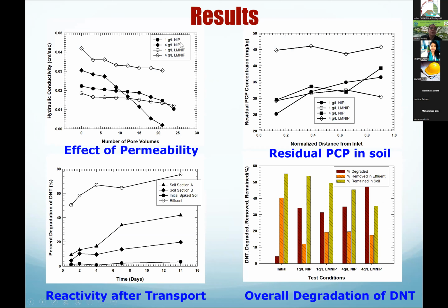So let's say I use 1 gram per liter nano iron particle, right? So here is unmodified 1 gram and 4 grams. With 1 gram, you don't see much reduction in the permeability, just slight reduction. But if I use 4 grams per liter unmodified nano iron particles, you see the permeability after certain pore volumes decreases significantly, because those particles got agglomerated and trapped, blocking the pores, blocking the porosity. Whereas if you use the 1 gram per liter lactate modified particles, that's this one, you see the permeability remains the same, slightly decreases, but it's okay. Even if I use a high 4 grams per liter lactate modified iron particles, the permeability remains high. And it's not clogging up like this one showing. If I use the bare nano iron particles of 4 grams per liter, it's going to clog up and it's not going to move further. Whereas with 4 grams per liter lactate modified, you see that permeability is maintained.